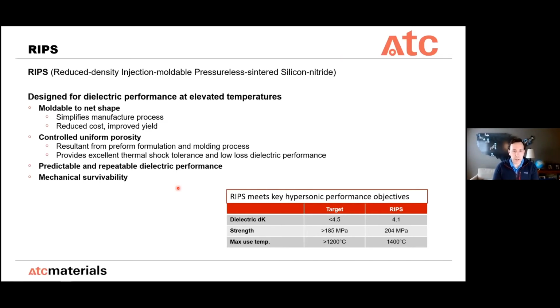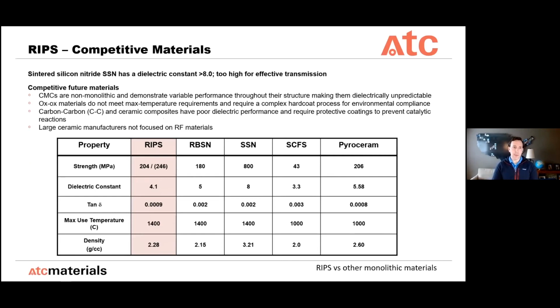So this is just a quick thing here without giving away all of the information that's been sent to us, but dielectric has to be under 4.5, strength greater than 185 at temperature, and a max use of 1200 to 1400 degrees C. And certainly our material meets or exceeds all of those different targets from the hypersonics community.